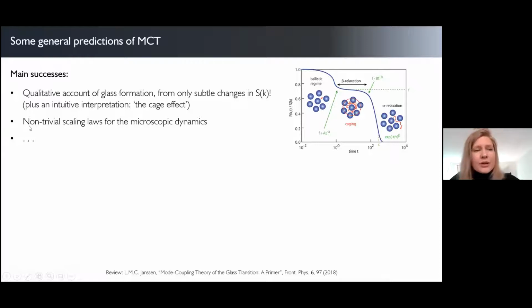And also another remarkable success of the theory is that it predicts certain universal scaling laws in the dynamics. In particular, for the experts in the audience, there are certain scaling laws in the so-called early beta regime, the late beta regime and the alpha relaxation regime. And mode coupling theory predicts that basically mathematically from the equations, and those scaling laws are found to be in very good agreement with both experimental and simulation data.